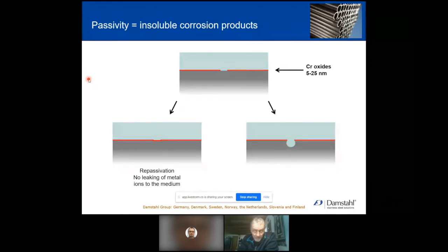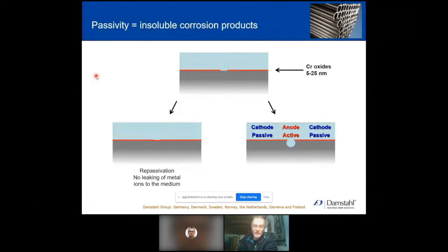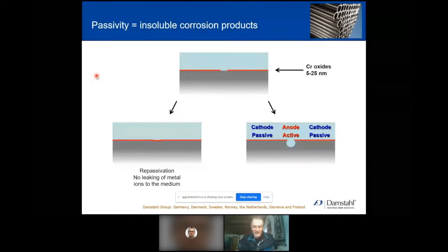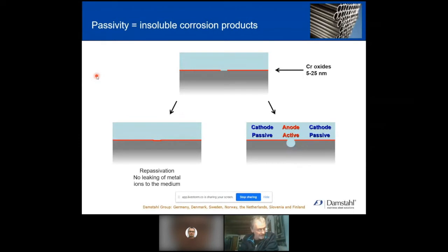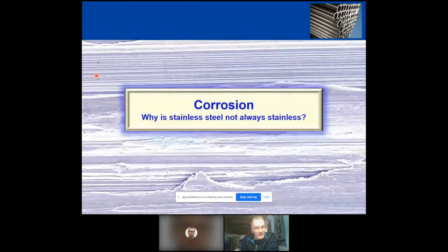But sometimes it doesn't. We get a local activation in the middle of all the passive surface, and then we have a very bad combination, which is a small anode and a large cathode, and we get a galvanic coupling and very quick local corrosion.